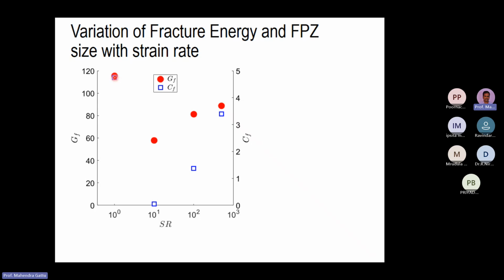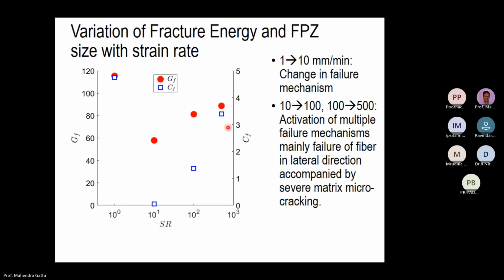Initially it is increasing, it is high, around 5 millimeters, and then it goes to 0, and then it is around between 1 and 2, and after that it is between 3 and 4. So this is what we observe. So we want to understand why this is happening. So to understand that, we look at the SEM imaging, that is the scanning electron microscope images of the failed specimens.